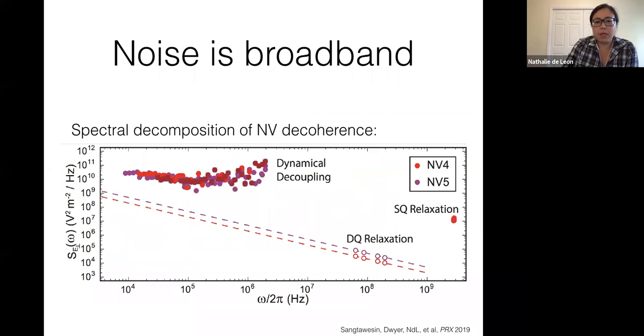Putting everything together, we can do spectral decomposition of this NV decoherence and plot what the spectrum of the noise looks like, and then put these single points in for our single and double quantum experiments as well. The dashed line is 1/f scaling for electric field noise so that you can actually compare these things directly. And we see that indeed it does look like we're dominated by magnetic noise over all of the relevant frequency range, and that this is a very white noise bath. So it looks like we're dealing with very broadband noise, even after we've done this last oxygen annealing step.